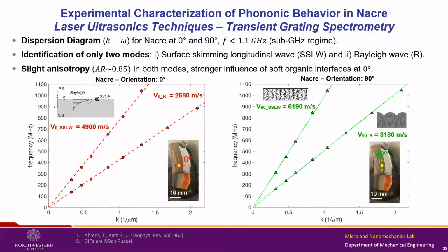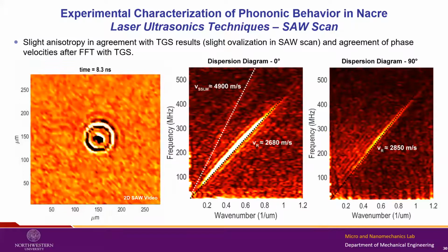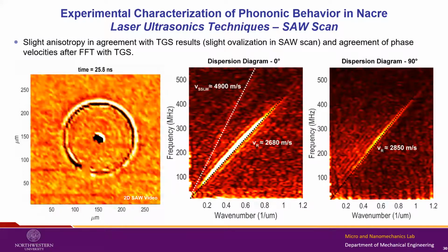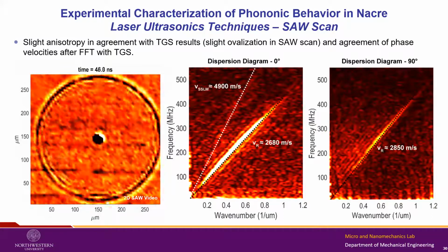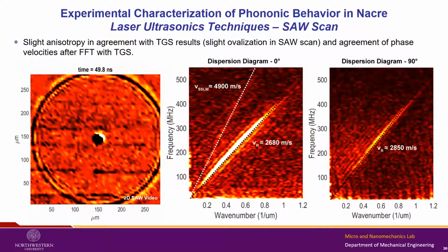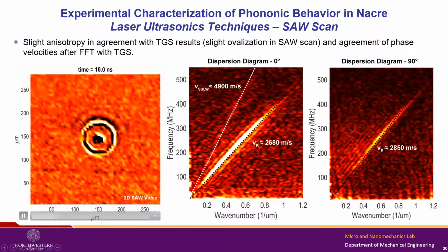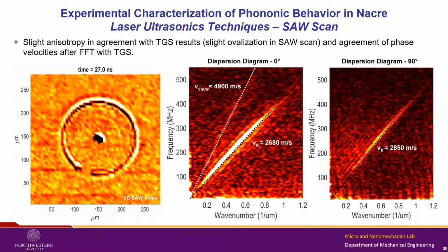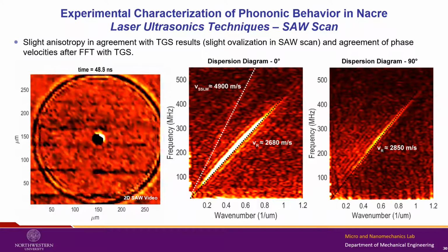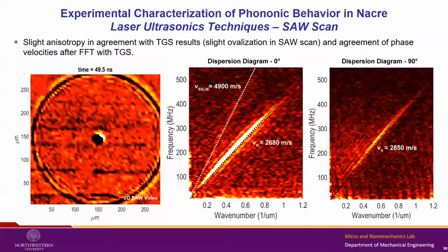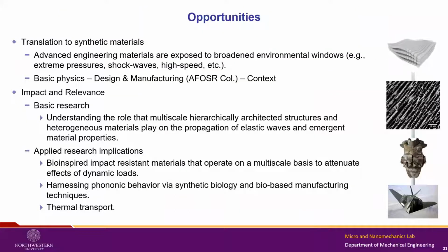But again, you can recreate the actual dispersion diagram of these materials using those techniques. And you can also create or see scans of how these surface acoustic waves propagate through the material. And with this, you can detect interesting phononic band gaps, because here I'm just showing a very simple movie in the actual nacre material, but you can filter this and you can map how the same propagation looks for different frequencies. And with that, you can identify phononic band gaps and interesting non-linear effects, as I was saying before. That's ongoing work, so I don't have a lot to show, but it would be interesting to show that connection and how we're studying it.